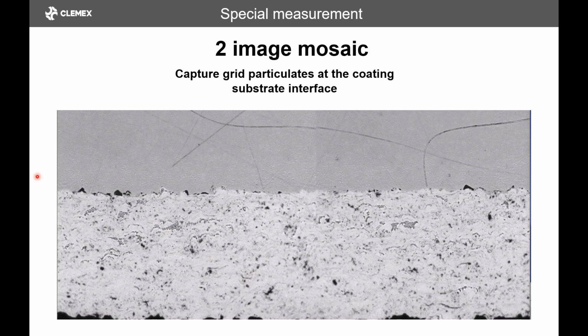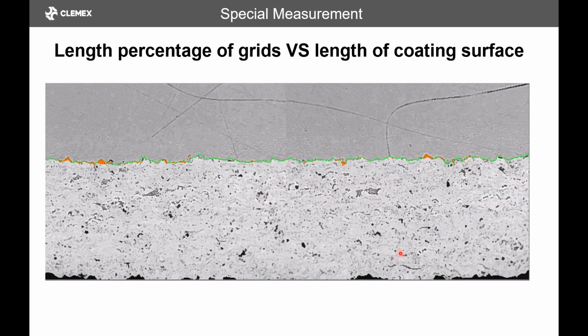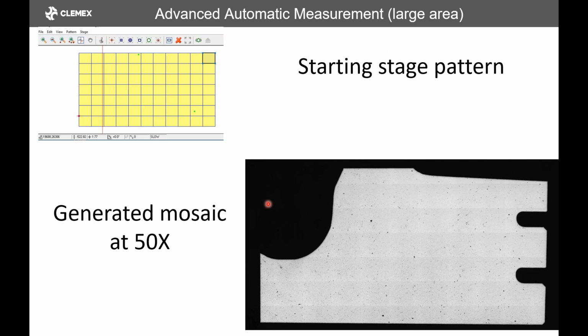Here we have another one, which is something done in the aerospace industry, where they need to measure remaining sandblast particles that would have been embedded into the sample. There's a certain ratio of length of those particles versus the whole length of the coating. There were 2 images stitched together because it needed to be a certain length. So we end up with this measurement where we have the line versus the line of the artifacts, or the inclusions. And the line of the inclusions versus the whole line is what is used as the final measurement.